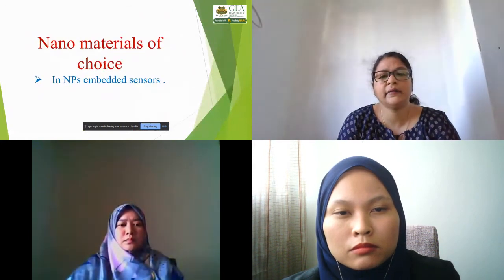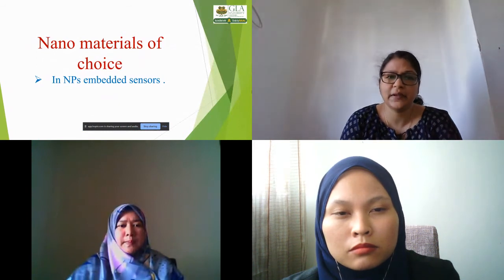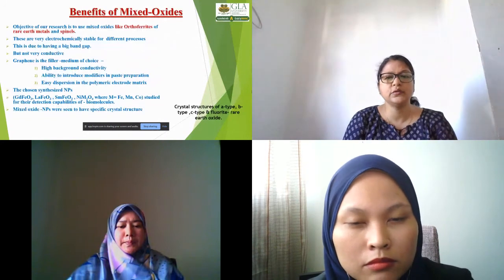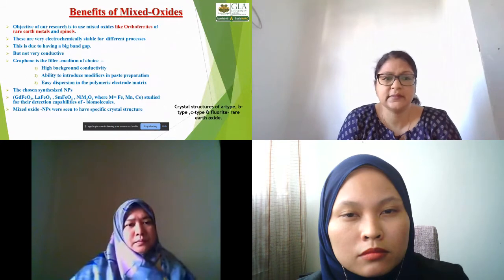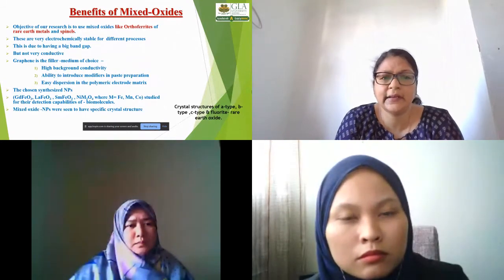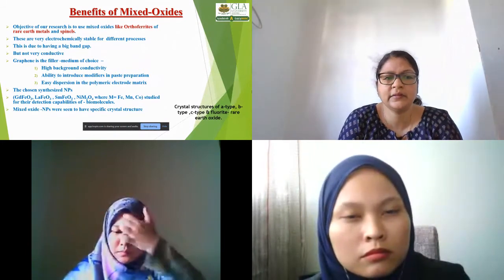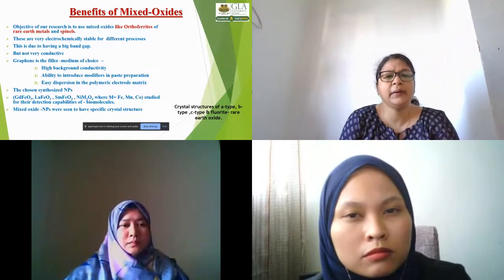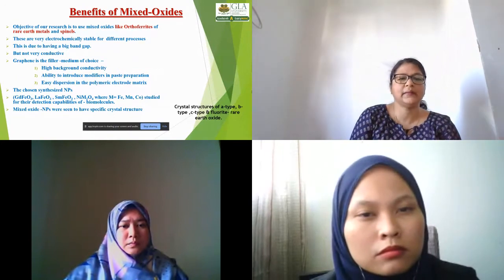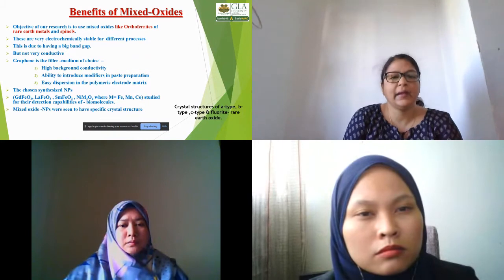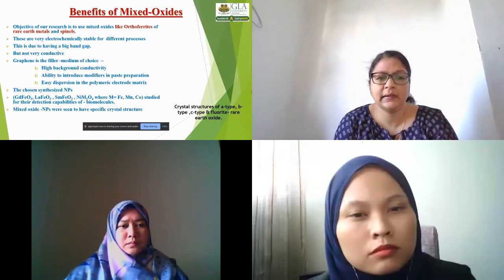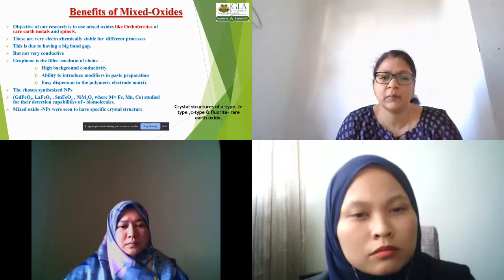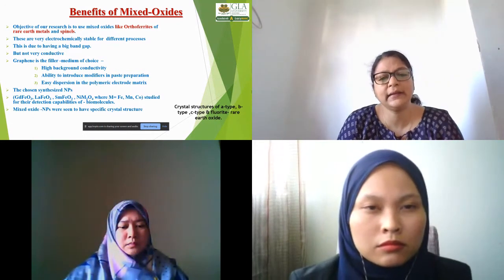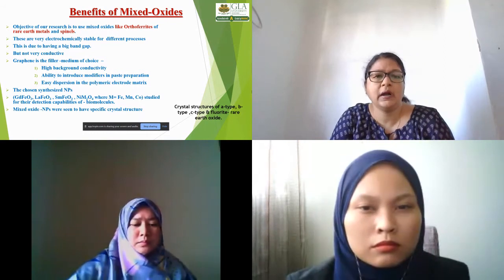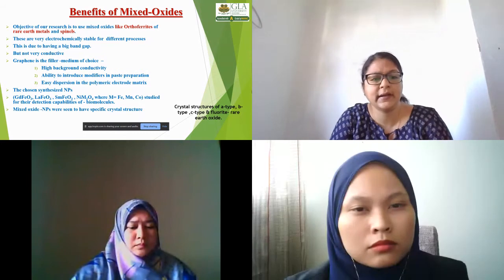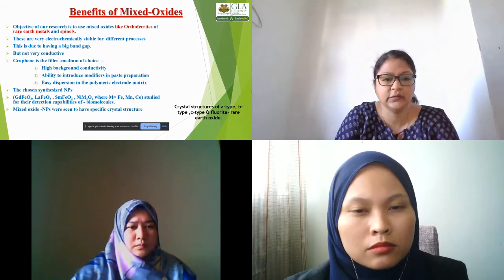In our project, the nanomaterials of choice were mixed oxides. In mixed oxides, we used orthoferrites of rare earth metals and spinels. The reason for choosing these is that they are very electrochemically stable for different processes, because they have a high band gap, but one issue is that they are not very conductive. So in order to make them conductive, graphene is used as a filler, because it has high background conductivity, can be easily used as a modifier in any paste preparation, and disperses well in any kind of polymeric matrix. In our project, we selectively chose gadolinium ferrate, lanthanum ferrate, samarium ferrate, and nickel manganate molecules.